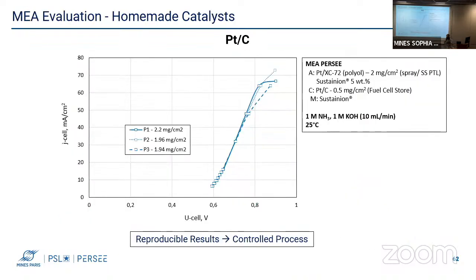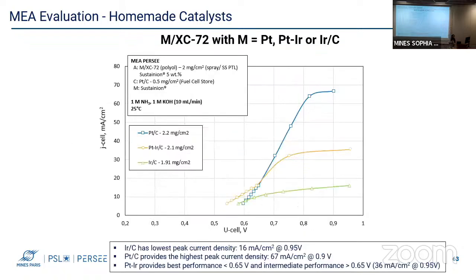Now we start by evaluating these catalysts, and we start with platinum on carbon. It was prepared at an anode loading of 2 milligram per centimeter square. 3 different PTLs were prepared in order to check for the reproducibility of the results, which were quite reproducible, which means that the catalyst synthesis and the spraying process were well controlled. We also evaluate the performance of the different prepared catalysts.